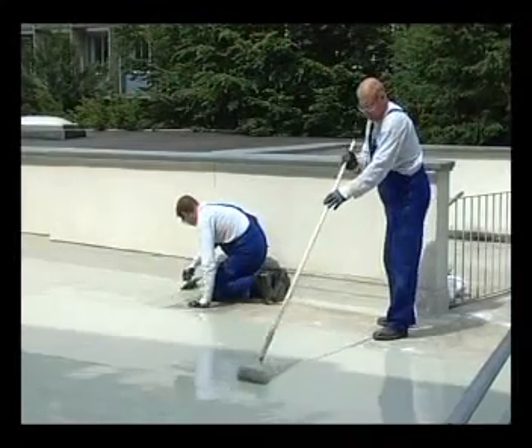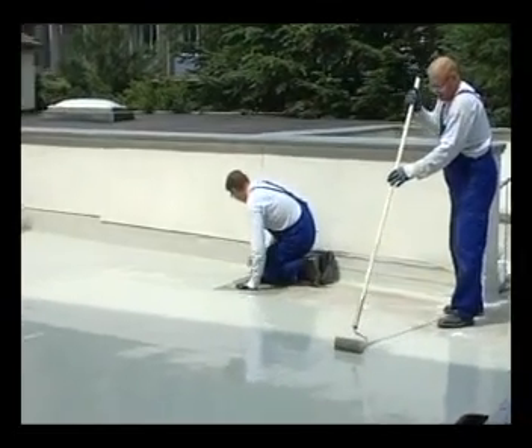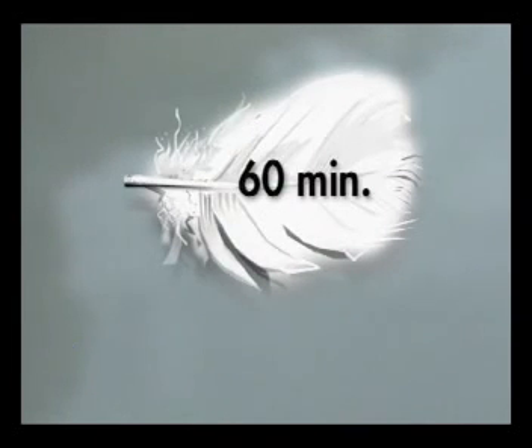Product usage for a layer thickness of 6 mm is 4 to 5 kilograms per square meter. At 20 degrees Celsius, the coated surface is rainproof after 35 minutes and can be walked on. You can continue with the final stage of the coating process, the top coat, after only an hour. The finish is used to seal the surface.